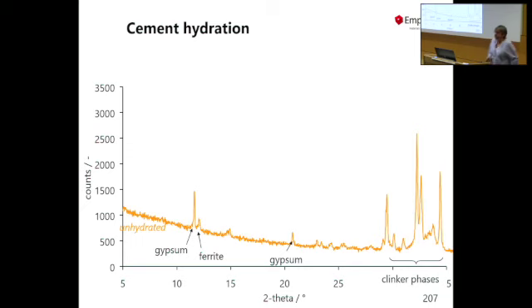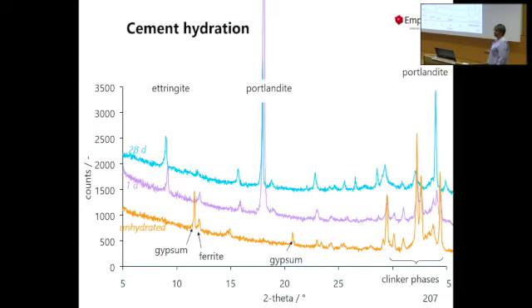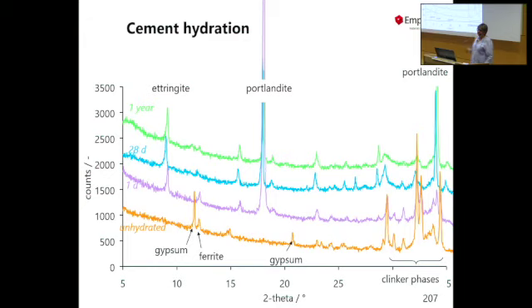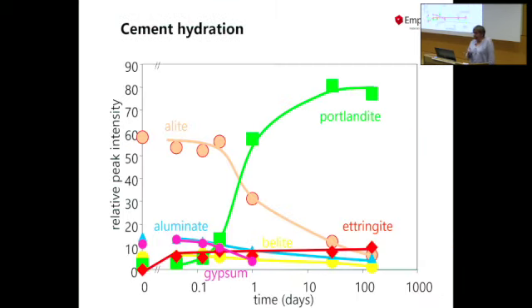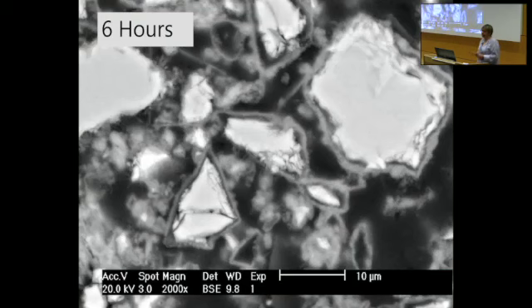Another way to use thermodynamic modeling is to look at cement hydration. This is just an XRD of a hydrating cement, where you see that the clinker reacts and we form Portlandite, ettringite, and CSH. We can also quantify it, and then we get graphs like that. Or we can look at it with the microscope, and then we see these beautiful pictures where we have the reacting clinkers, the hydrates that grow on top of them, and after a few hours they start to connect and we get our concrete strength.